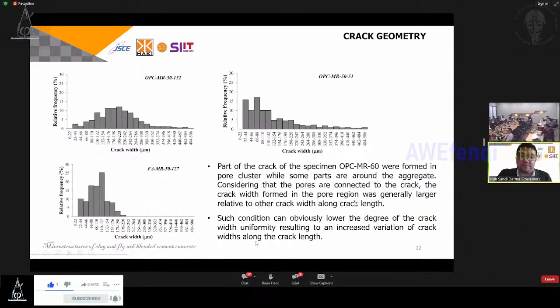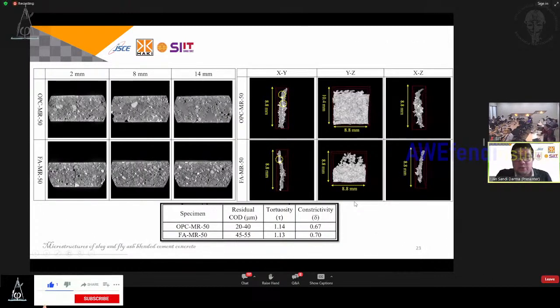And for the flexural specimen, we also calculate, we do clustering, and then we will have the crack in 3D dimension. As you can see here, the tortuosity is quite low compared to the splitting. So here we can summarize that flexural cracks result in lower tortuosity compared to the splitting specimen, and also constrictivity is quite high compared to the splitting test.